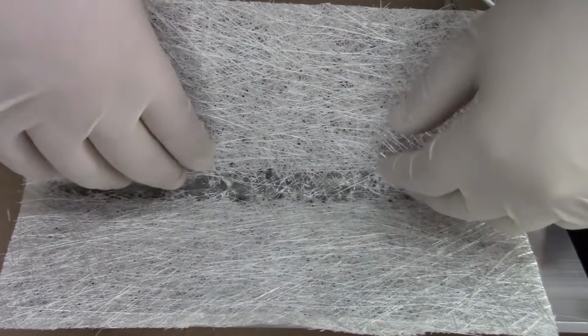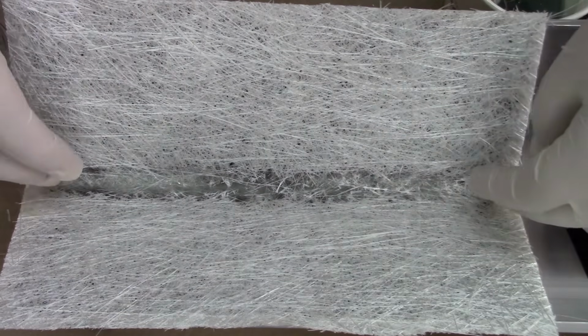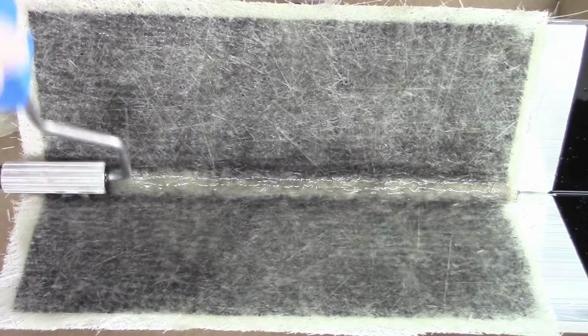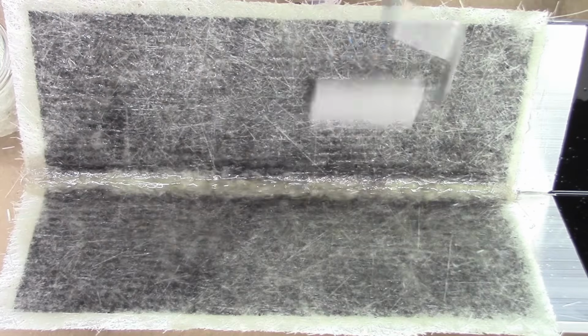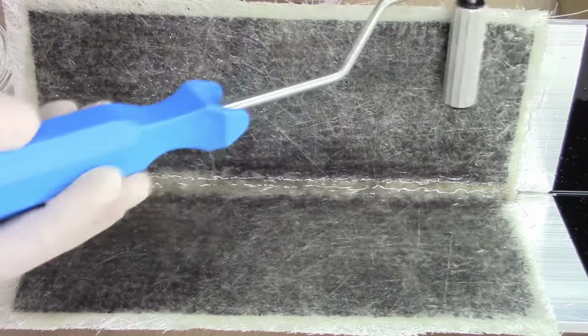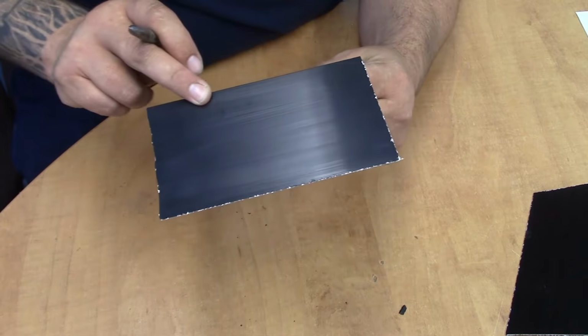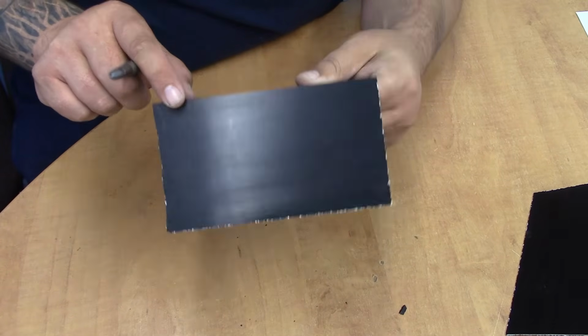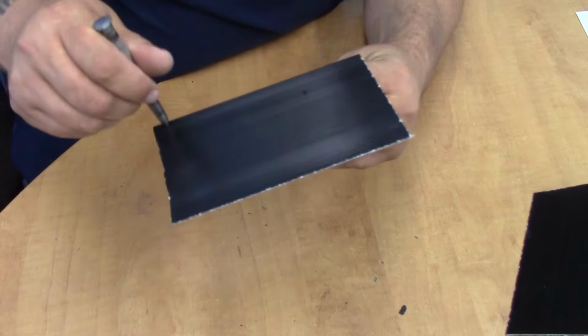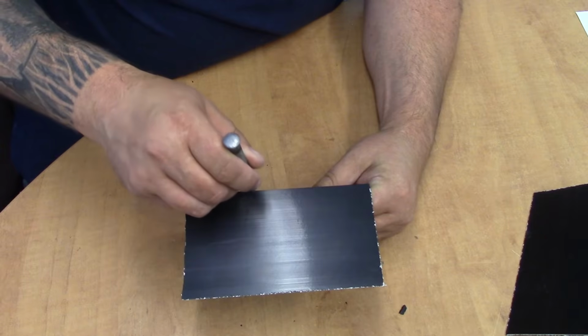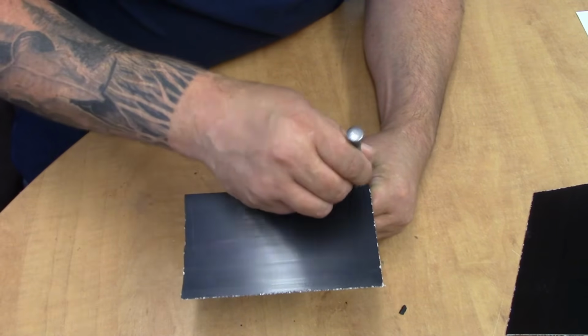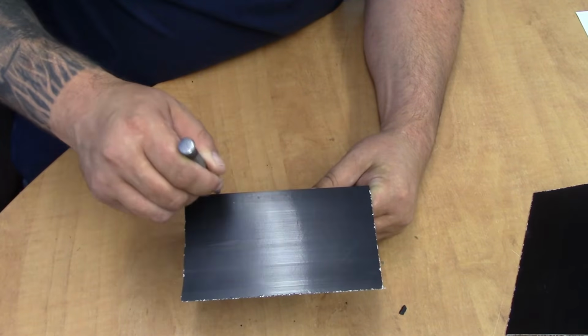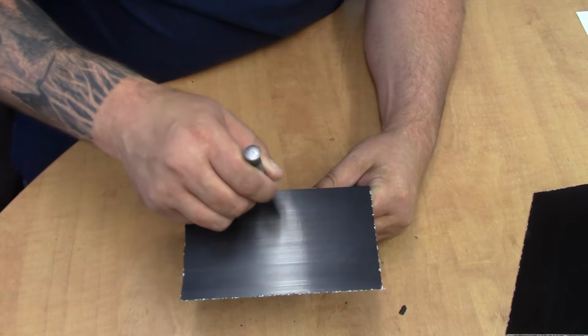Then we apply our matting over the top and complete our laminate, consolidating the resin and matting and follow on with a radius roller into the corner. This method tends to be the most professional, as it ensures direct contact of glass fibre against the gel coat. We see no blisters in our cured sample, and even after tapping with a sharp tool for inspection, there are no weak areas or voids found.